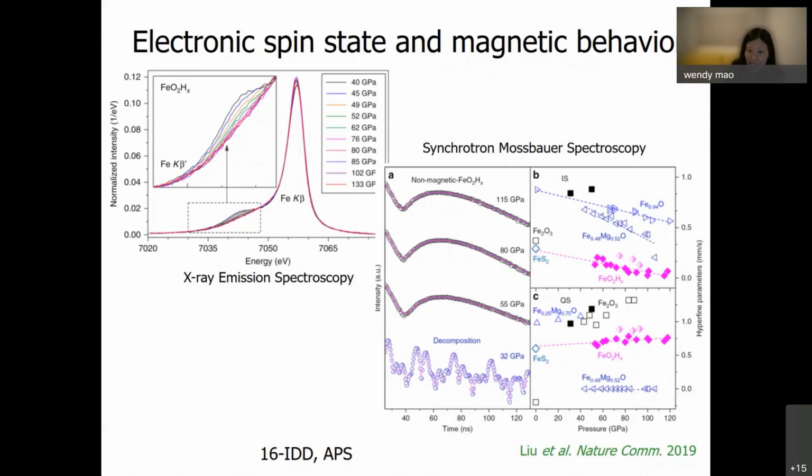And then we also collected a series of synchrotron Mossbauer spectroscopy spectra, which consistently show, in the FeO2 with both hydrogen and hydrogen-free versions, a non-magnetic state, represented by these clean single-peak spectra. The spectra were analyzed using the CONUSS program to extract the quadrupole splitting and the isomer shift for iron in the FeO2. The values for both the quadrupole splitting and the isomer shift were very consistent with FeS2 if extrapolated back to ambient pressure.